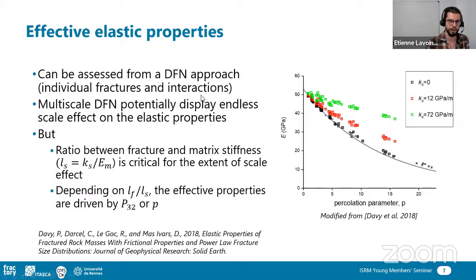a DFN approach, because given a DFN, we are able to recover with a semi-analytical solution the displacement that happens on the fracture. And we're able to quantify the contribution of each fracture, depending on its orientation and the loading of the mechanical parameters, to the total deformation, accounting for interactions because we consider that each fracture sees an effective medium.